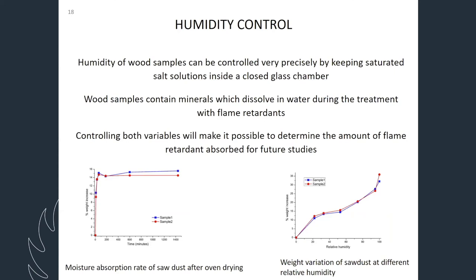Now we talk about the humidity control, because in a later part we realized we need to control the humidity of the sample in order to understand the exact weight of wood and how much moisture it retains. So if you see the graph in the left bottom, we took the wood and we kept it in the oven for 1 hour. Then I took the weight of the wood and it decreased from the original one. But if I kept it for a longer period, I saw the weight of the wood is not decreasing anymore. So it means all the moisture leaves the wood sample after 1 hour.